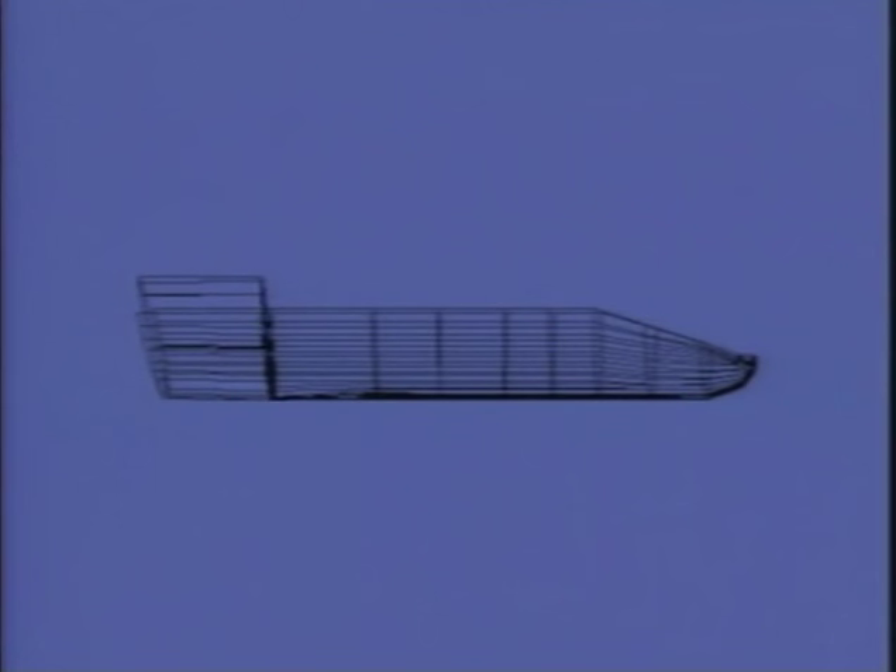The layup we are about to document is the lower shell of the Super Mileage Racer. This was more complex than the upper unit and will serve as a better instructional tool because this shell will be made in two cures. We will first laminate the outer skin and vacuum bag it until fully cured. After it is cured and the vacuum bagging materials are removed, the honeycomb and inner plies will be bonded in place. We do not recommend laminating a full sheet of honeycomb into the outer skin when using wet layup techniques because the cells will fill with resin.